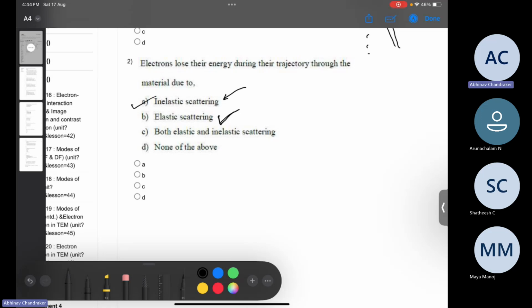Because it is encountering these charged electrons around it, when the primary electron beam is going through the specimen, there will be some loss in energy by formation of electromagnetic waves such as continuum X-rays or characteristic X-rays, which happens when the energy of electrons is absorbed and the electrons get excited, and this excitation can lead to emission of a characteristic X-ray later on.